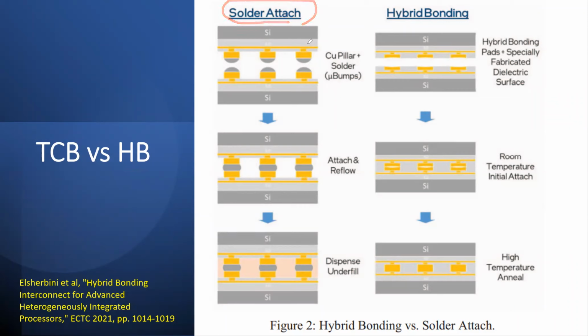Here in thermal compression, there's a copper pillar and then there's a solder. The solder is on top of the copper and then you press it down, all right? And then you reflow it. You heat up to some temperature to melt, not exactly melt but semi-melt the solder. A reflow means that the solid becomes a liquid-like material at a temperature below the melting temperature, like your eutectic temperature, something like that. Right? Then you fill it up.